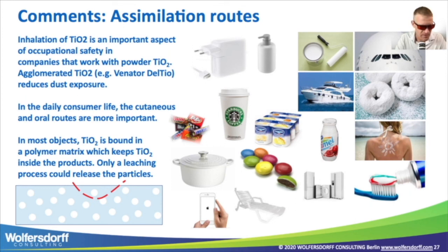There's one interesting feature. Sometimes in architectural outdoor coatings, non-durable pigments are used. The reason for that is called the chalking effect. What happens can be explained with a sketch I put in the left-hand bottom. This is the sketch of the paint or polymer film, and you have in white the titanium dioxide crystals. Now, what happens if the titanium dioxide crystals do not protect the polymer matrix, and then the polymer matrix is broken down? Then, like indicated, we have the titanium dioxide powder on the surface of the paint film, and that is leading towards some kind of self-cleaning effect of the coating. It certainly makes a matte surface, but also a self-cleaning surface, and that could be desired in outdoor coatings.